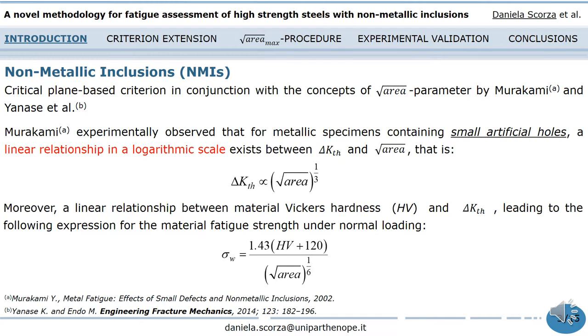In order to consider the influence of such inclusions in estimating the fatigue lifetime, a critical plane-based criterion, such as the Carpinteri et al. criterion, may be employed in conjunction with the concept of square root area, proposed by Murakami and Yanase. The concept of square root area was first introduced by Murakami et al., when, after a large experimental campaign on metallic specimens containing small artificial holes, they observed that the size of the defect was crucial to determine the fatigue strength, mainly in high-strength metals.